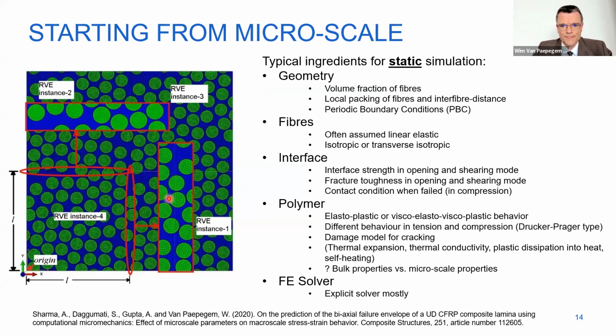So it's periodic. The fibers are typically assumed linear elastic because most of these simulations are done in transverse loading in this plane. And then the interface, that becomes a bit problematic. We need to define an interface strength in mode 1 and mode 2. We also need to define a fracture toughness for crack propagation in that interface. And if the interface has failed and you apply, for example, compressive loading, we also need to define a contact condition, possibly with a friction coefficient.